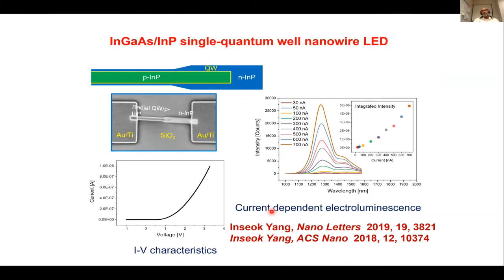So till now, I've only shown you optically pumped nanowire lasers, but ultimately industry wants electrically pumped nanowire lasers. And in fact, this is the work of Dr. Inseok Yang, who is from Samsung, and then came and again returned to Samsung, where he's a research engineer. So you can see that he spent a lot of time trying to make PN junctions. I told you that you need a PN junction to make an electrically injected laser or LED. So he doped this indium phosphide with zinc to make P-type indium phosphide. He grew an indium gallium arsenide quantum well, and then made the N-type indium phosphide on the top, and then transferred them to a glass slide and made electrical contacts using electron beam lithography, using titanium and gold on both ends.